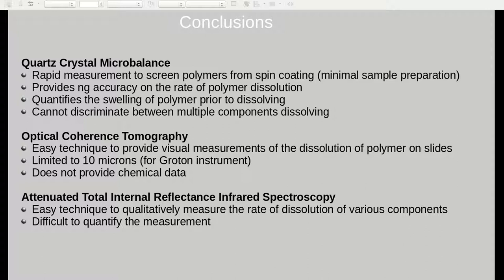OCT provides an excellent way to visualize the way the polymer film swells and subsequently dissolves in situ. The current instrument in Groton is limited to approximately 10 microns for a film thickness. However, other instruments with varying bandwidth can increase this resolution. As with QCM, OCT does not provide any chemical data.